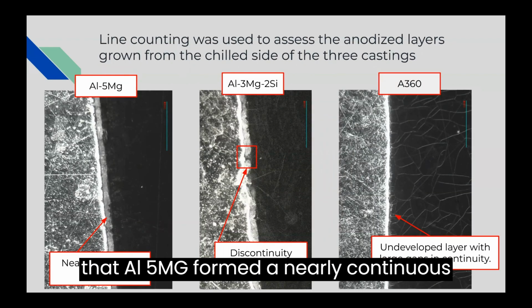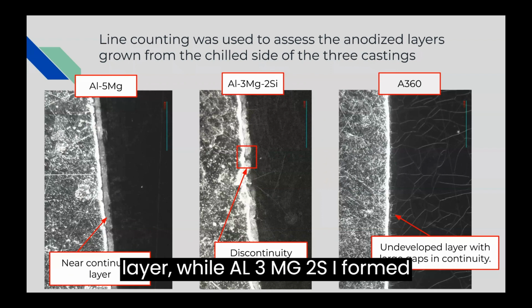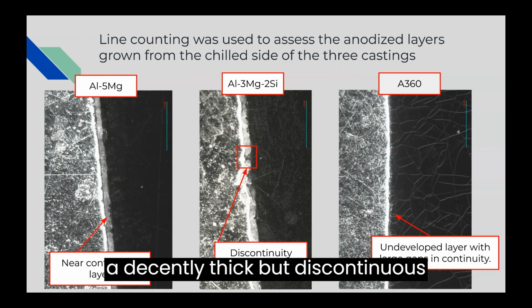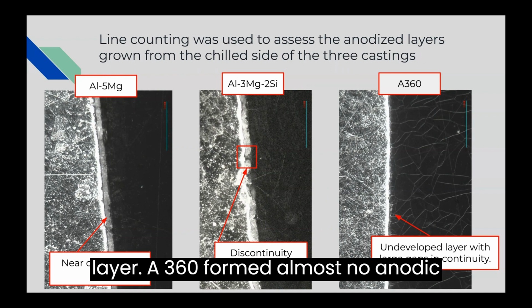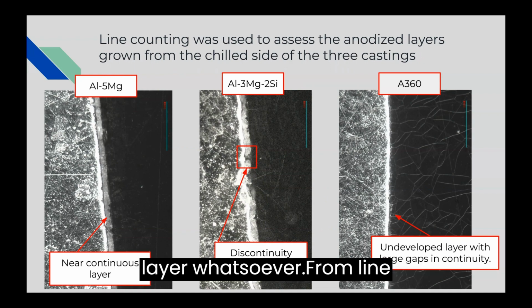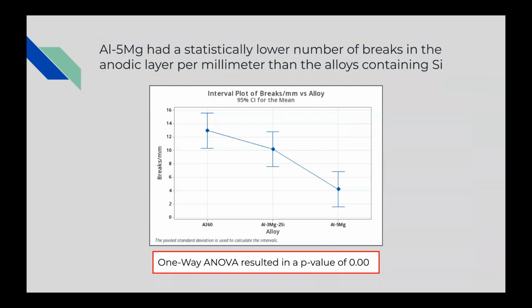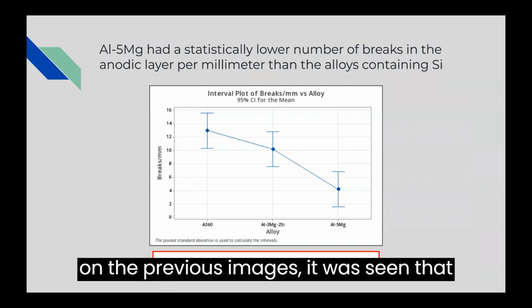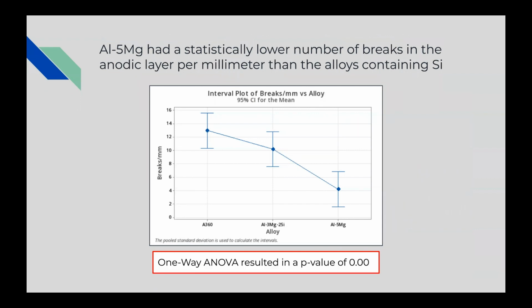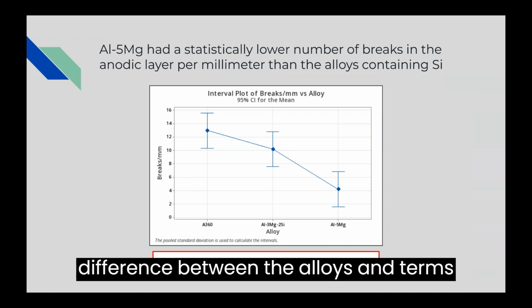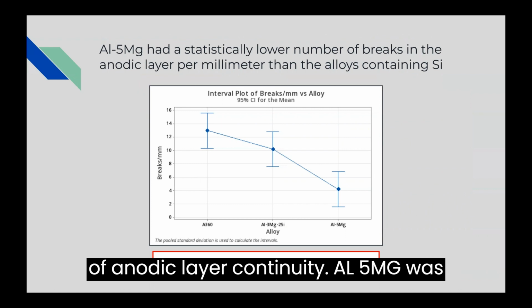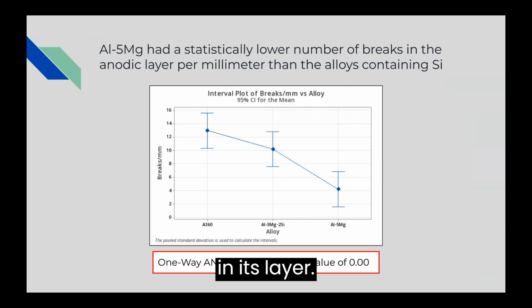It was seen that Al5Mg formed a nearly continuous layer, while Al3Mg2Si formed a decently thick but discontinuous layer. A360 formed almost no anodic layer whatsoever. From line counting of breaks in the anodic layer on the previous images, it was seen that there was a statistically significant difference between the alloys in terms of anodic layer continuity. Al5Mg was seen to have the least amount of breaks in its layer.